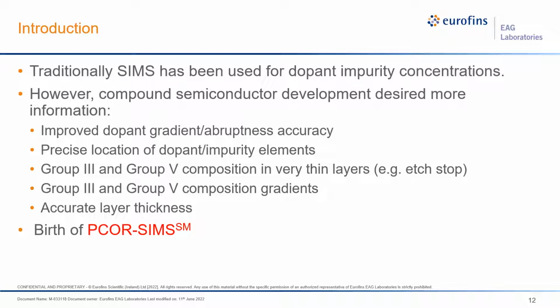Traditionally, SIMS has been used for dopant and impurity concentrations. However, compound semiconductor development has desired more information: improved dopant gradient and abruptness accuracy, precise location of dopant and impurity elements, group 3 and group 5 composition in very thin layers, for instance an etch stop, group 3 and group 5 composition gradient analysis, and accurate layer thicknesses. However, most SIMS analyses are carried out in a matrix of fixed composition, i.e. silicon or gallium arsenide. 3-5 materials present unique difficulties because the matrix often changes with depth. This change in matrix composition changes elemental sensitivities, changing sputter rates. It changes everything. This is certainly the case when analyzing VCSELs by SIMS. And for that, we invented PCOR-SIMS, shown in red at the bottom of the slide.